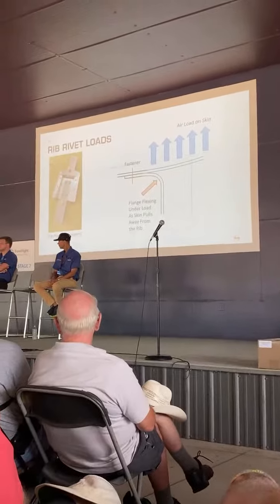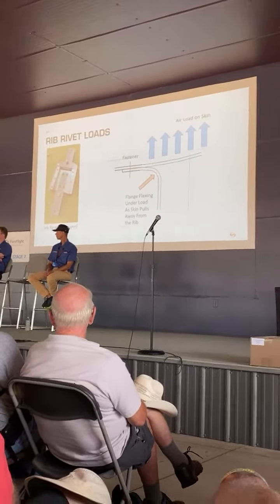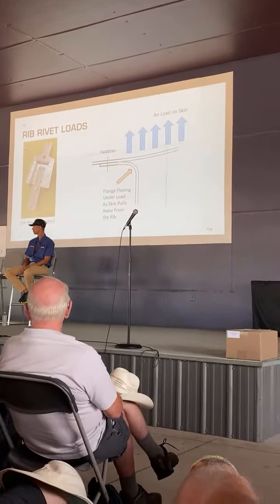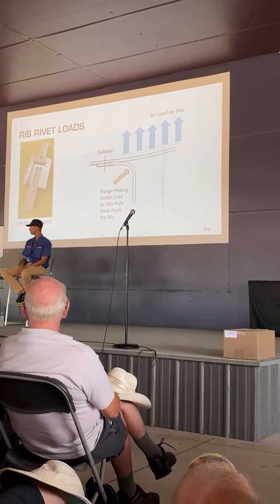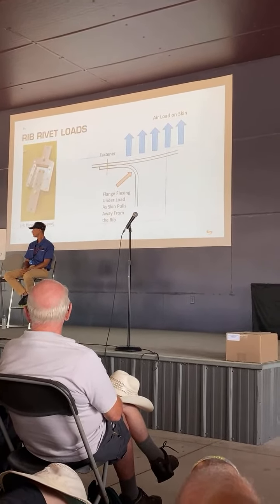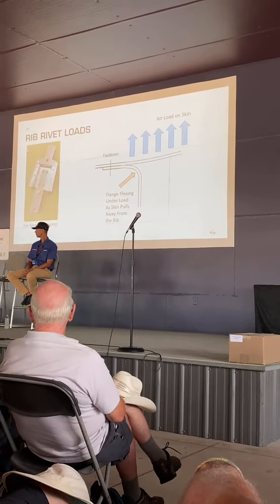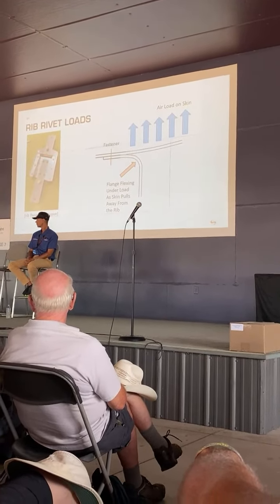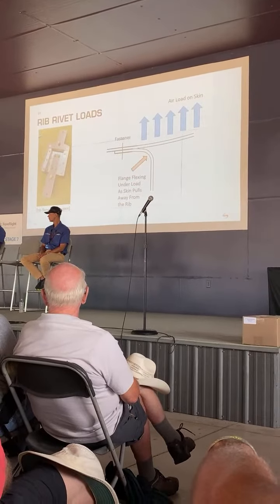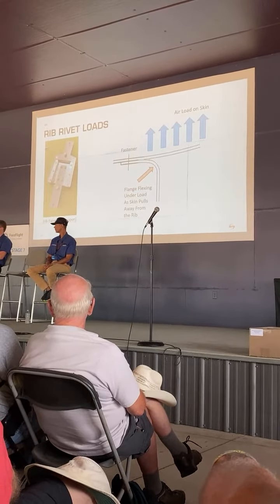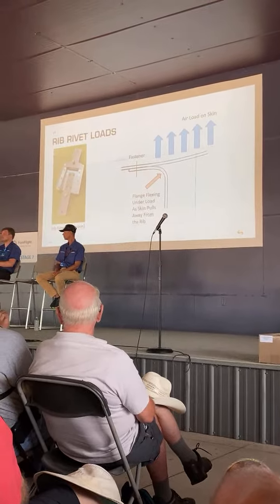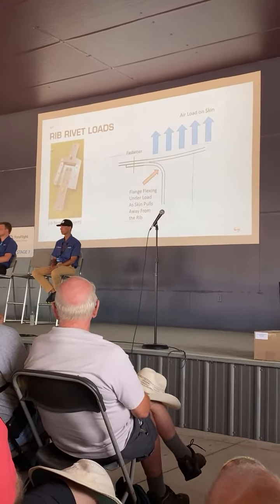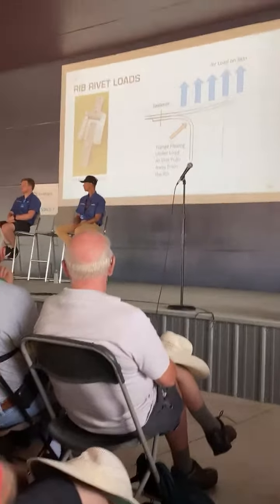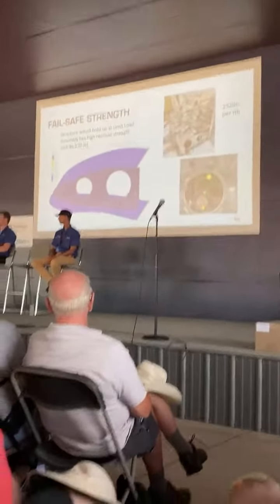We'll also add notches in this, but what we're really curious about is the fact that as you apply an air load in between ribs, so the skin is being pulled up, there's actually a peeling load and it opens up and closes the flange of the rib repeatedly. So we want to know if the notch is going to fail first, the rib flange is going to fail first, or a hole with a feature in it, or holes with features in them, will fail first. So that test is starting this week. We're just finishing up the coupon test and moving on to these other tests.